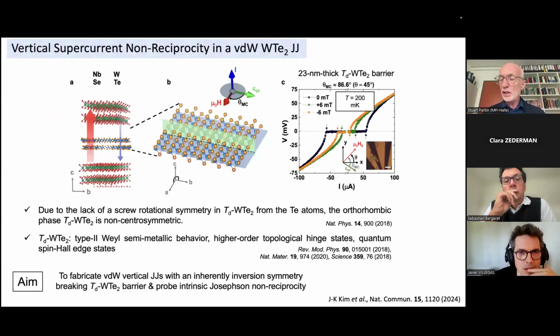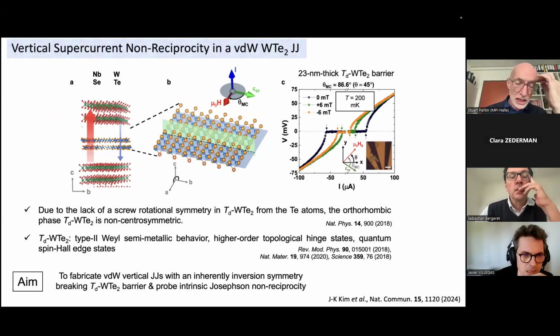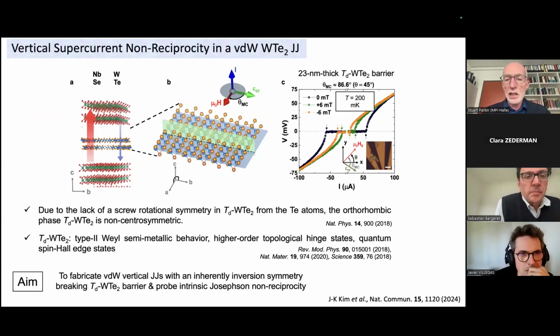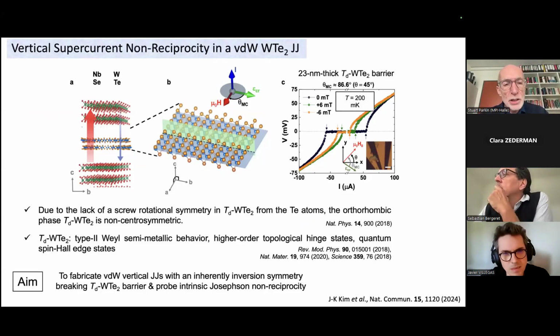Now, finally, in the last few minutes, let me just talk about one other experiment, which is some work we published last year. This is by Jae-Kun Kim, a postdoc in my group. And what he has done is we've now grown a vertical tunnel junction, all van der Waals materials. So here we're using niobium diselenide. 2H niobium diselenide is a very interesting superconducting material. We're using relatively thick layers as the top and bottom superconducting layers. And in between, we're putting layers of tungsten ditelluride.